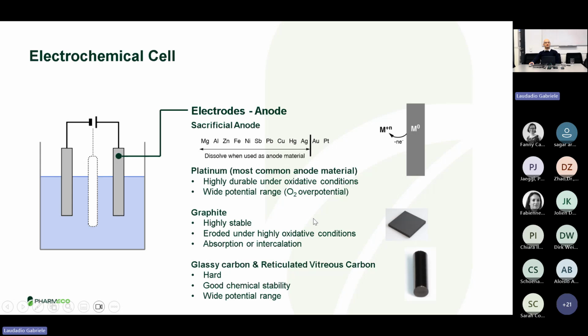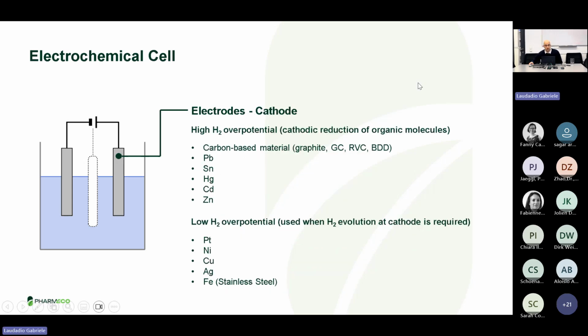In case we are not really interested in the oxidation part, so we would like, for example, to reduce our compounds, we can also choose anodes that get basically oxidized over time. So the metal zero gets slowly oxidized, and the ions get dissolved in the solution. These kinds of electrodes are called sacrificial anodes, and they tend to be more reactive depending on their redox potential. So we can also select the potential range where we work based on the material that we are using.